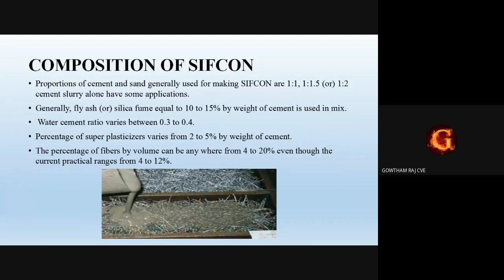This is the composition of SIFCON. The cement and sand are in the proportion of either 1:1, 1:2 or 1:1.5. Additives such as fly ash or silica fume can be 10 to 15% of the weight of cement used in the mix. Water cement ratio is 0.3 to 0.4. The percentage of plasticizers can vary from 2 to 5% depending upon the weight of the cement.